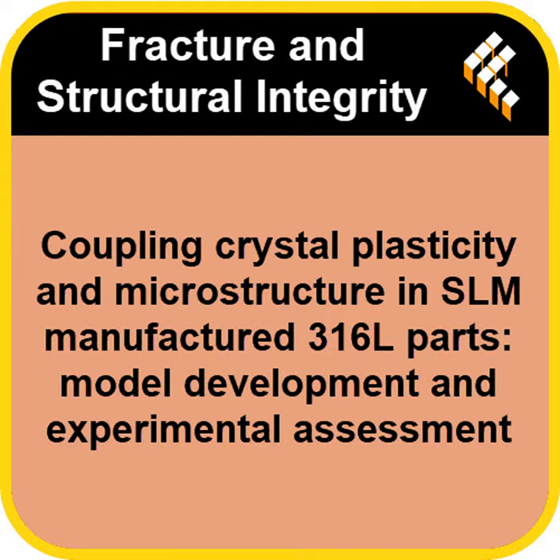For the soft slip systems, the main barrier is the big grain boundary. So the mean free path, we'll call it D, is set by the grain size, so 120 microns. Okay, the biggest barrier dominates for the easy paths. Right. But for those rigid slip systems, the primary barrier is those tiny built-in laser tempering twins. So for those paths, D is set by the twin distance, which the model pegs at just 0.345 microns. This huge difference in scale is what gives the model its accuracy. It covers the internal structure.